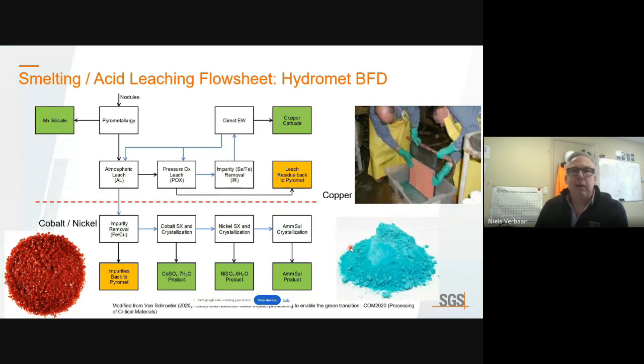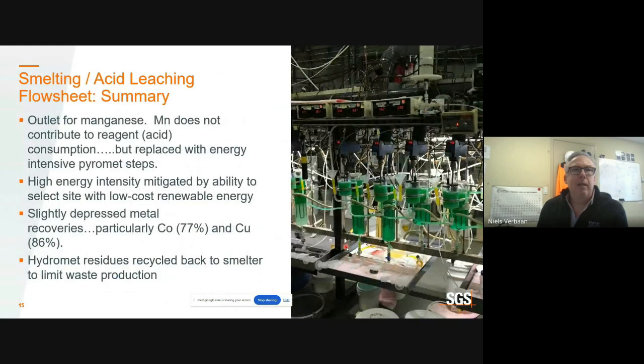Okay, and let's see if I can get to the next slide. So if I can summarize the smelting acid leaching flow sheet, there's a good outlet here for manganese. It doesn't contribute to the reagent consumption, but obviously it's been replaced with a highly energy intensive pyrometallurgical step. Although they'd probably say that the high energy intensity has been mitigated by the ability to select a site with low cost renewable energy.